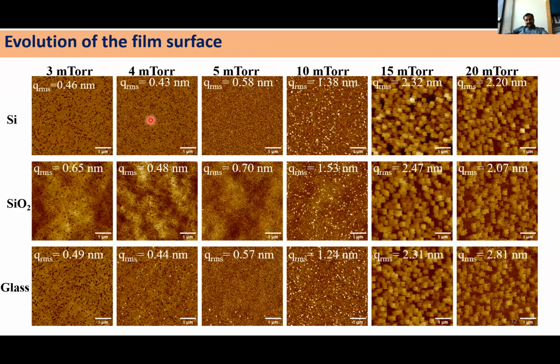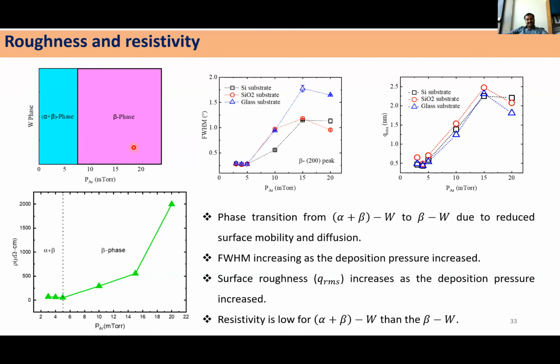And we have taken the thin film surface, and we found that the roughness is increasing when you keep on increasing the background argon pressure during the deposition. This can be understood because when we are increasing the argon pressure, the mean free path of the tungsten atoms that are getting sputtered towards the substrate is going to decrease. So when the mean free path decreases, the kinetic energy also decreases. So it prefers more of an island growth that increases the roughness. And that is also the cause for getting a beta phase, which is a metastable phase as compared to the mixed phase. And we have measured the resistivity, and we found that the mixed phase has lower resistivity as compared to the beta phase. And as you keep on increasing the pressure, the resistivity is also increasing.